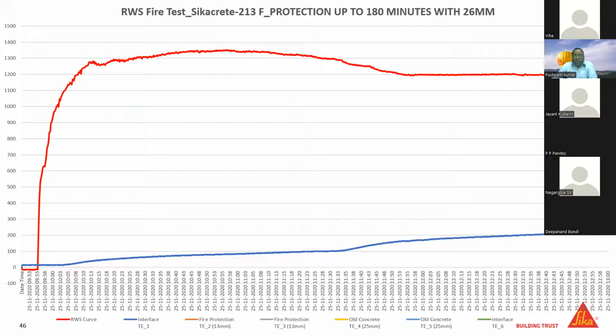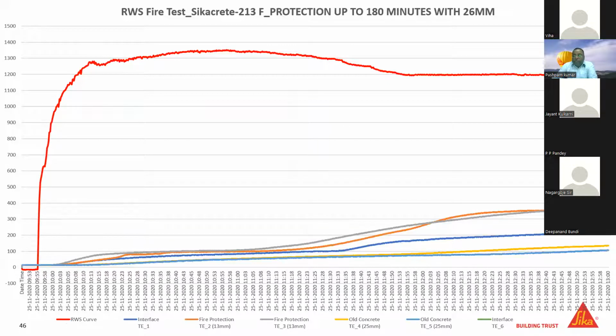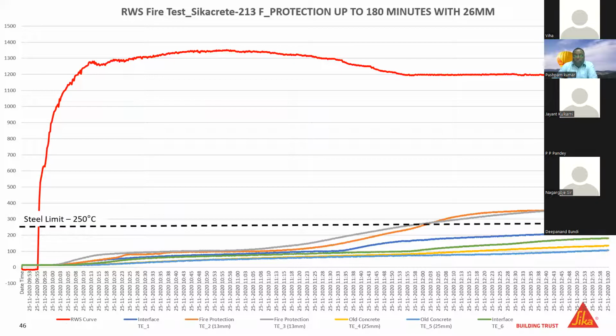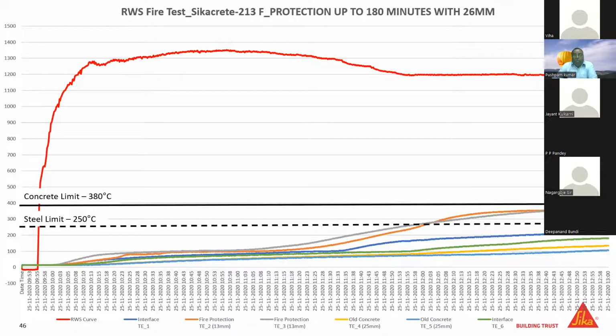So you can see thermocouples 1, 2, 3, 4, 5, 6, and therein this is tested against limits. For steel, the limit is 250 degrees centigrade. It should not exceed 250 degrees centigrade at the steel temperature, or the concrete interface temperature should not exceed 380 degrees centigrade. So you can see this is tested for a 3-hour fire rating, and the temperature is within the defined limit.